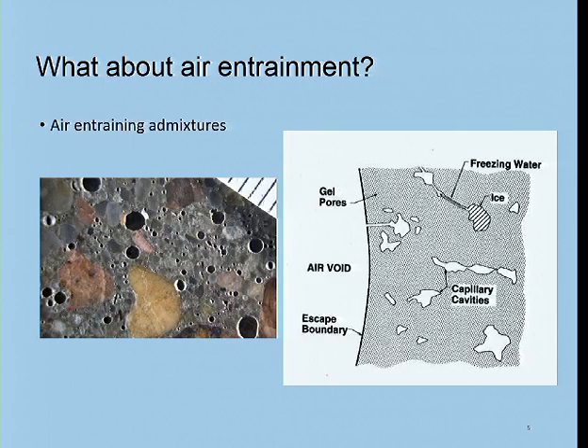And the concept goes that we want the water that exists in the very, very fine capillary pores of concrete material to have a bleed channel, a relief channel, moving toward this air void. So this channel, this boundary, is a boundary with an air void. The bubble is, you know, huge, way beyond the size of the screen. And so if there's water inside these capillary pores that wants to turn to ice, that pressure can be relieved if there's a path outward. And by having these little air bubbles present in the microstructure, we essentially give that kind of pressure relief.